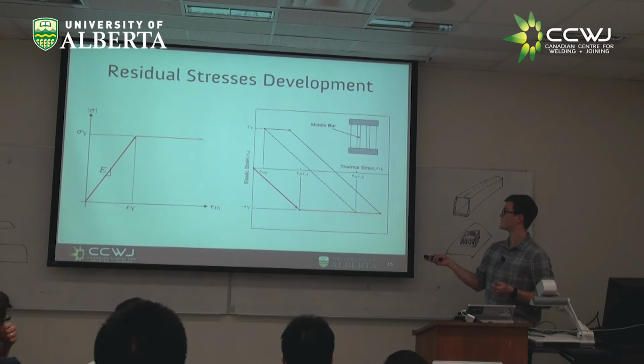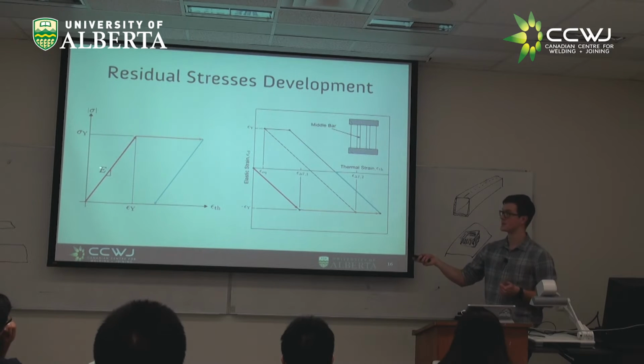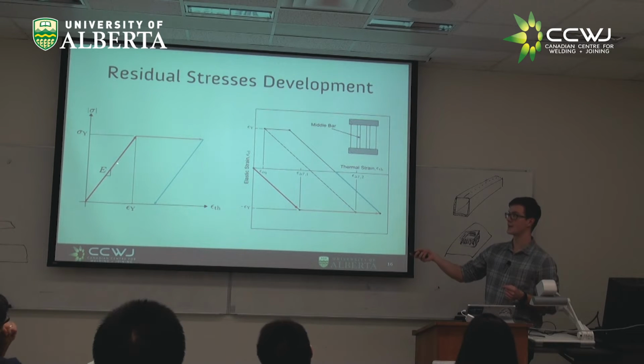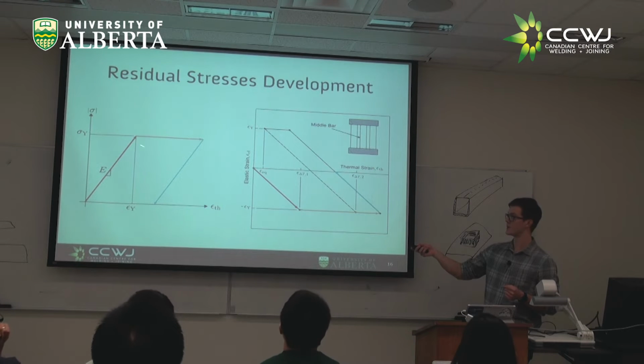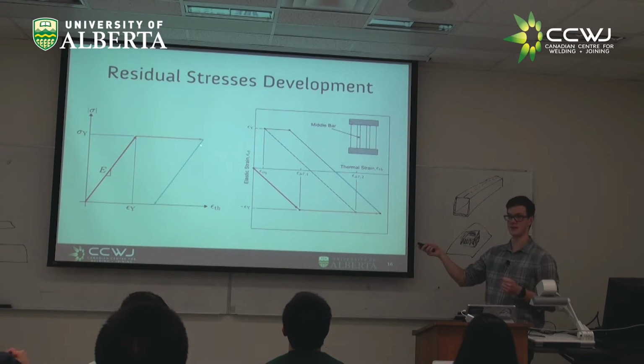So now if we go back to, in this case, we return back to a zero stress state, it's because we've cooled a bit. So to recap, we start at some initial temperature. We're going to heat up, developing strain elastically. At some point, we're going to reach a yield stress or yield strain, and we're going to keep at that constant level as we still develop more thermal strain. Then we hit our peak. Now, as we start to cool from our peak, we're going to be recovering that strain elastically. This is exactly what you see in a stress strain curve if you stop it at some plastic strain before failure and then allow your material to recover back to a zero stress state.